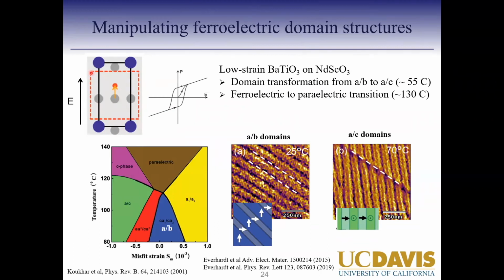Just a reminder, ferroelectric materials lack an inversion symmetry. So if you have a cubic system that goes through distortions, which results in a tetragonal phase, the center atom, for example titanium in this case, would shift up or down and break the inversion symmetry. And as it shifts up or down compared to the gray oxygens, that would create a permanent dipole, which gives the polarization of a ferroelectric material.